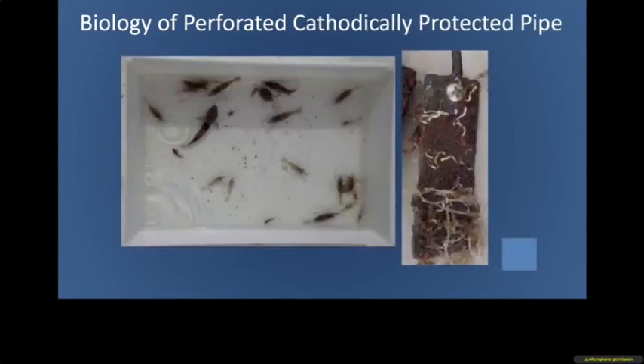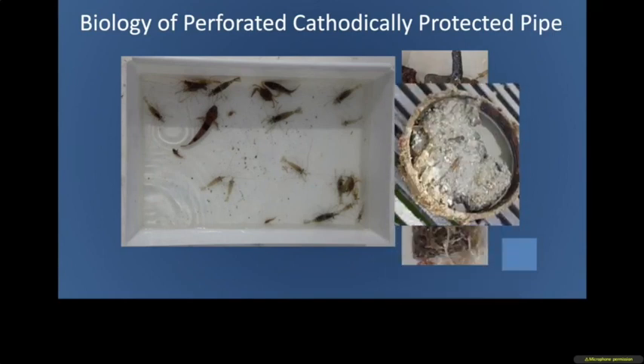But if we go to the perforated cathodically protected pipes, we found a really rich assemblage of both free-swimming and benthic organisms. And the other interesting thing was the sediments at the bottom of the pipe were very healthy, because they were not being inundated with dead and decaying biology from the sides of the pipe.